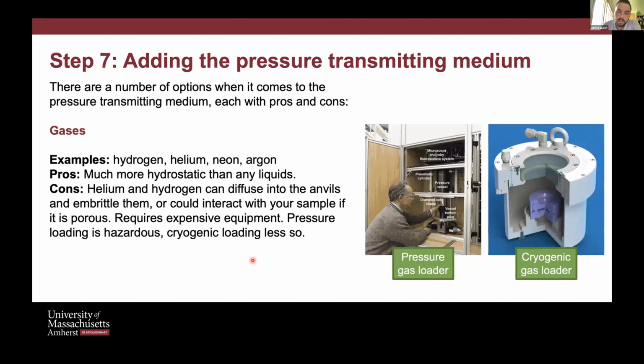So the best way to do it, if you can, and this might mean sending an email to people who have one of these two ways of doing gas loading, but really the gold standard for data for single crystal would be loading with hydrogen or helium, you know, a light gas, because that's going to give you a hydrostatic medium to the highest pressures. And when we say hydrostatic or quasi-hydrostatic, we mean not that the pressure is equal in all of the sample space, that's not really achievable, but that at any point, in other words, at the crystal, the pressure that it's experiencing is the same.